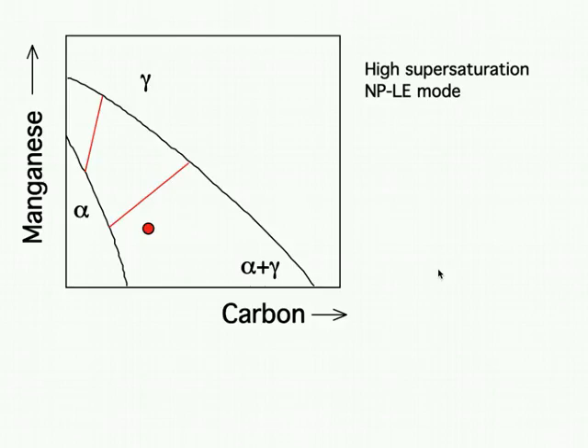Let's do a construction in which the ferrite forms without much partitioning of manganese. In other words, the negligible partitioning, local equilibrium mode of transformation. So we start with a fully austenitic sample at high temperatures, and then we quench it into the alpha plus gamma phase field at some location which is close to the alpha boundary.